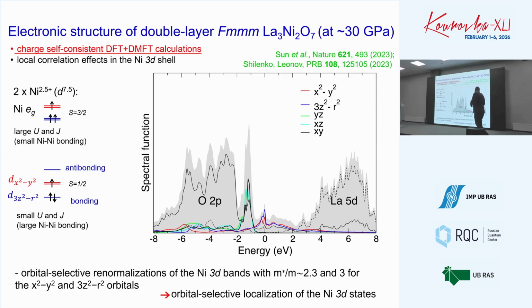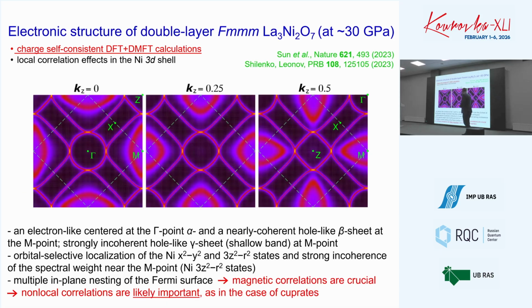Well, this is again the story about renormalizations. This material shows strongly orbital-dependent quasi-particle renormalizations. So this e_g state, again nested Fermi surface, although we do see some kind of very incoherent state due to this z-square orbital, which touches the Fermi surface near the M-point.